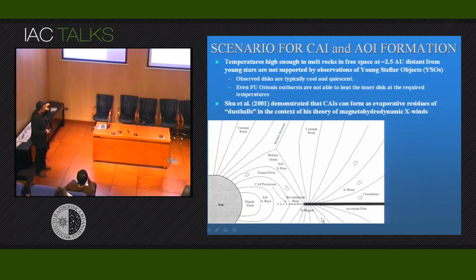That's the reason, because we have evidence that these CAIs are compact materials mostly made of calcium aluminium oxides and suffered different degrees of heating. In fact, most of them have different layers, a good evidence that they were heated and reheated several times. The typical time scales